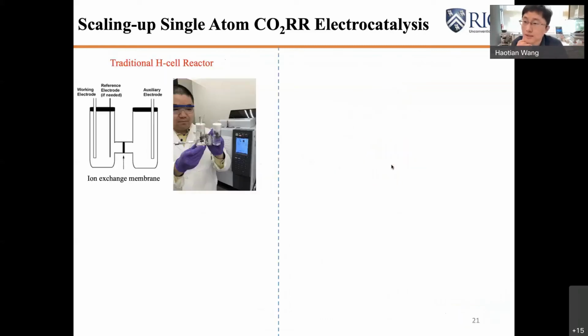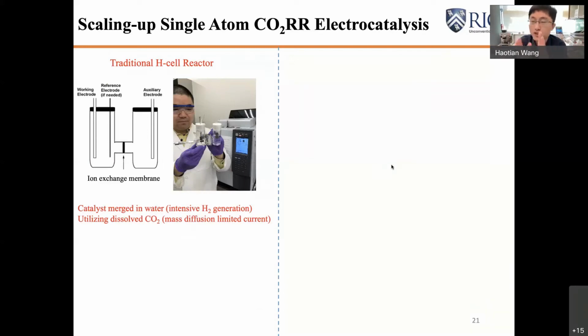And the second step to scale up this process is the current density. In most of the previous studies in CO2 reduction, people generally used this type of H cell. So basically what we do is we have the catalyst electrode, we immerse that in the water, and we bubble that water with CO2. So basically the CO2 gets reduced on the surface of the catalyst, and these are the CO2 molecules that are dissolved in water. So imagine that concentration compared to the water, you might get more than 99.99% of surrounding molecules are water, and only trace amounts of molecules are CO2.